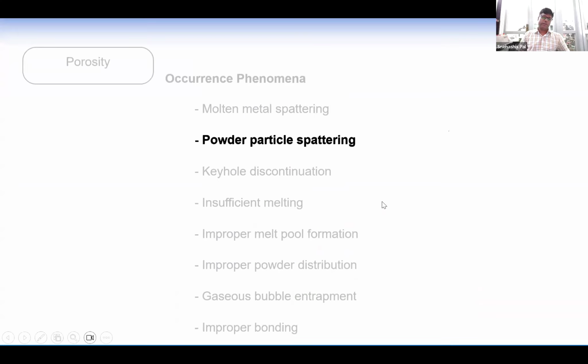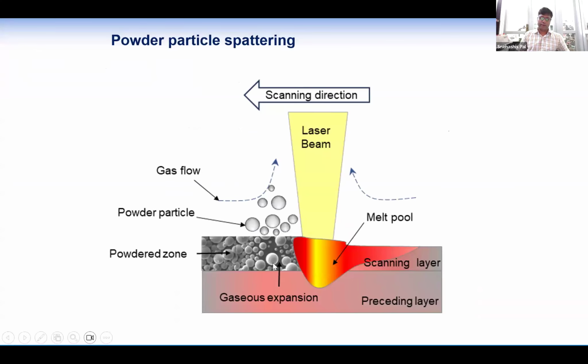and then make a porosity. And also powder particles from the action zone, let's say from here, can go out due to the heat shock, or due to the expansion of the interparticular gas. It can expand suddenly at the velocity of the scanning speed, which can be 1000 millimeter per second. So a lot of heat shock occurs there. That's why the powder particles can move out. Also, there will be a cyclone here.